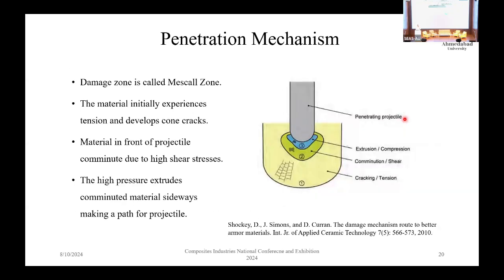The moment the bullet hits, there will be a zone of compression. So there is a projectile, and when it touches the ceramic, it will try to create a zone of compression. As a result of this compression, a stress wave will travel along the depth direction till the end of the specimen, and that will lead to shearing and compression of the material ahead of it. That will result in pulverization, converting the ceramic back into powder or pieces at least. In turn, that will lead to tensile phenomena. We are trying to bend a specimen, and we already discussed that ceramics are very poor in tension.